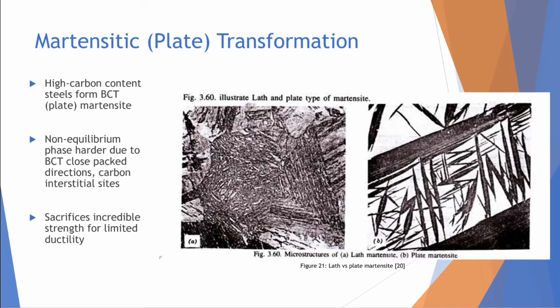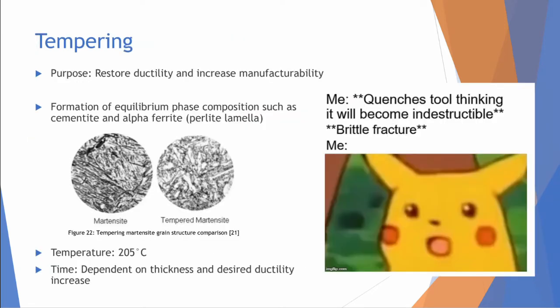This is important as plate martensite is very hard as its body-centered tetragonal crystal structure contains no close-packed slip planes on which dislocations can move easily. Furthermore, interstitial sites are occupied by carbon atoms which additionally restrict dislocation movement. Once quenched, the steel is extremely hard but very brittle. In order to restore some ductility, the hardened material must undergo tempering.